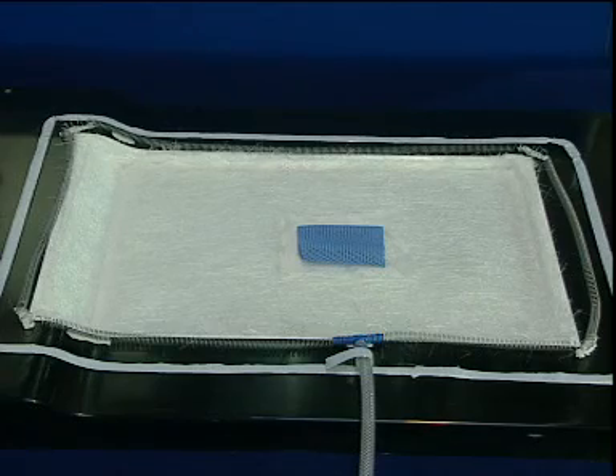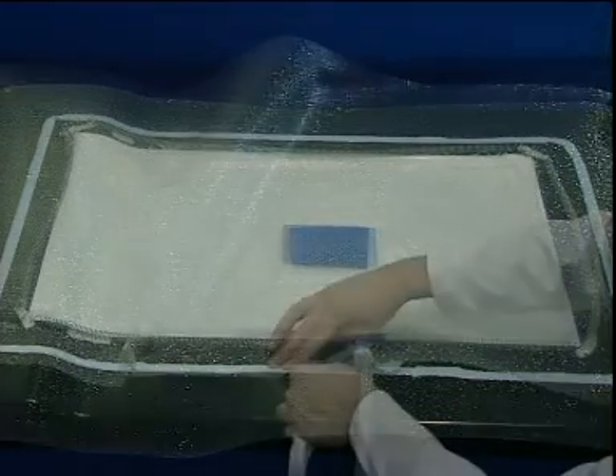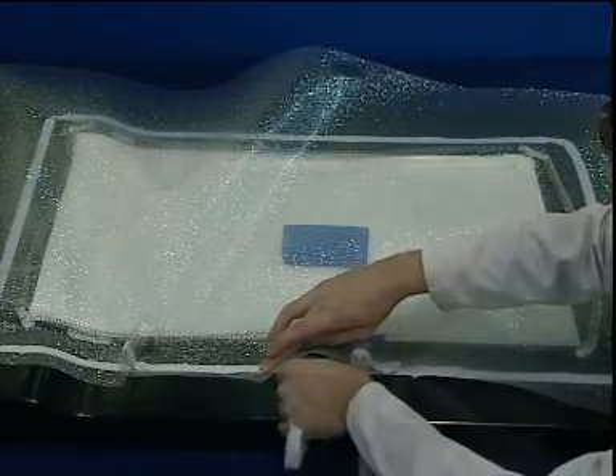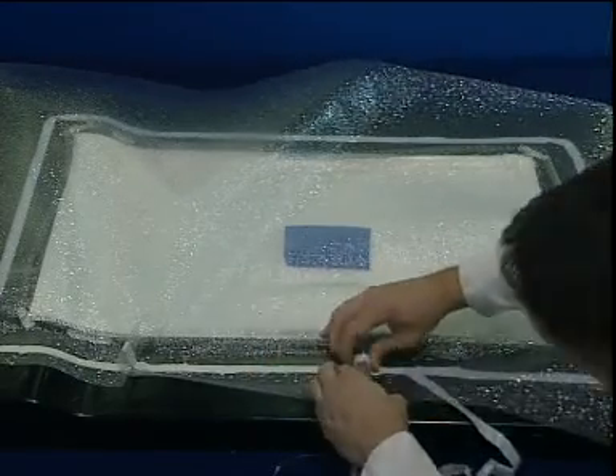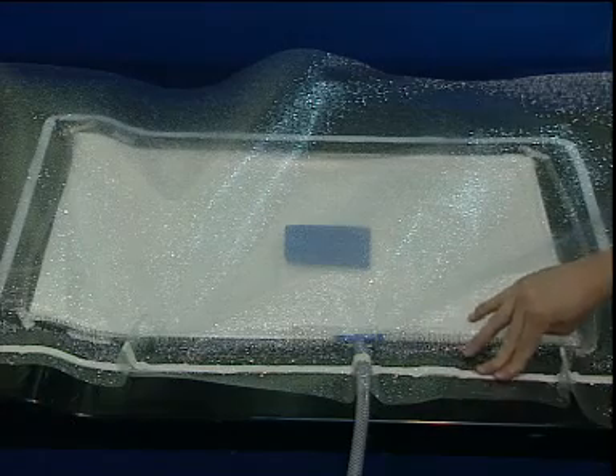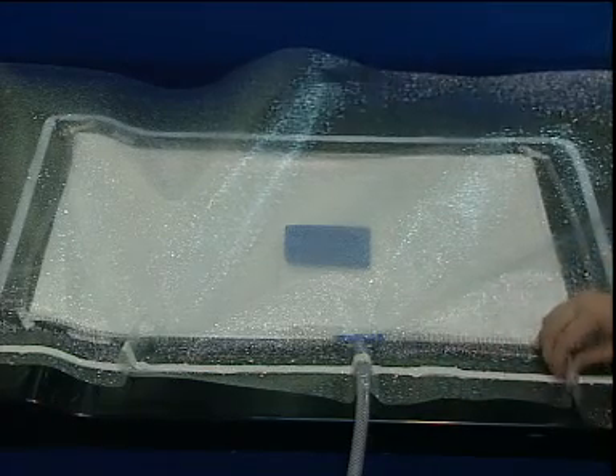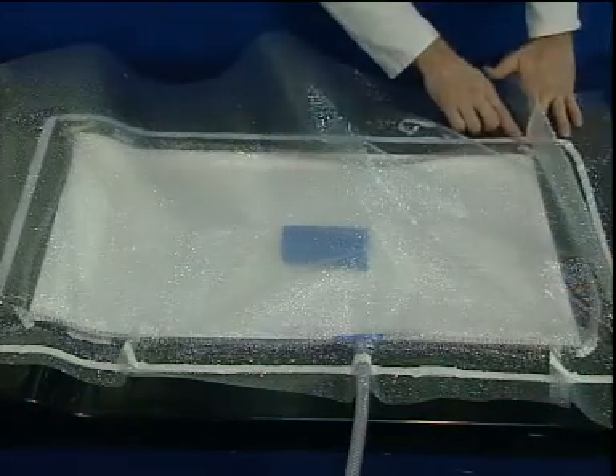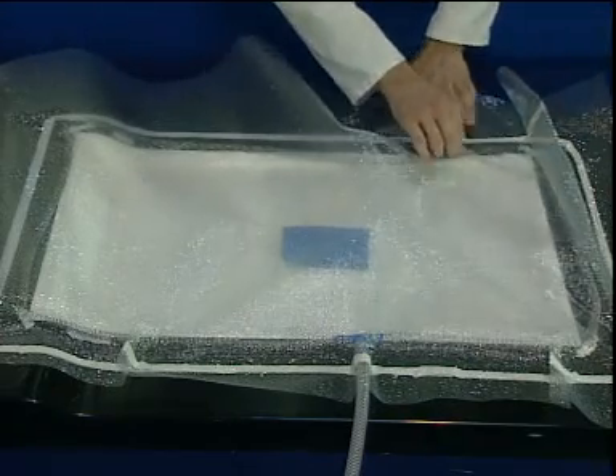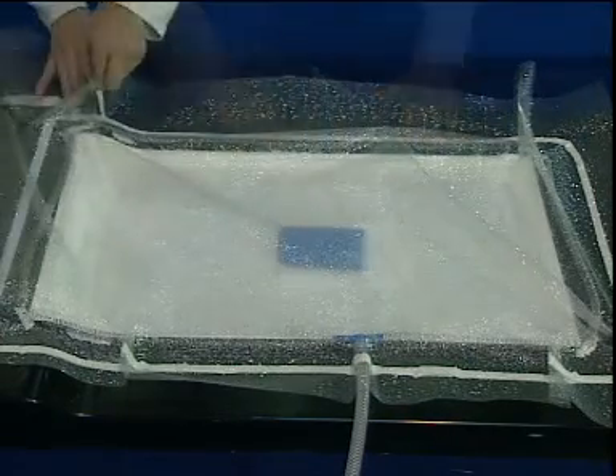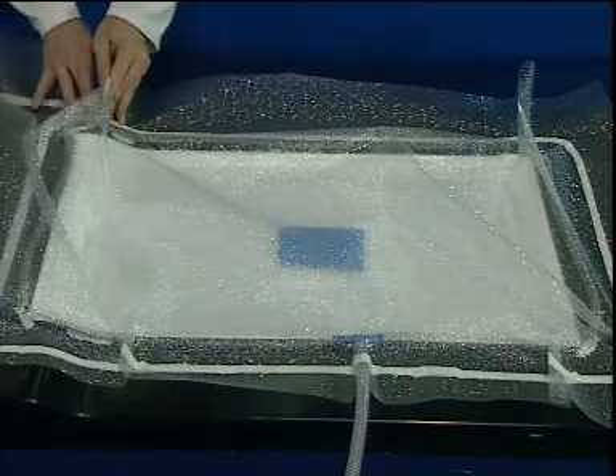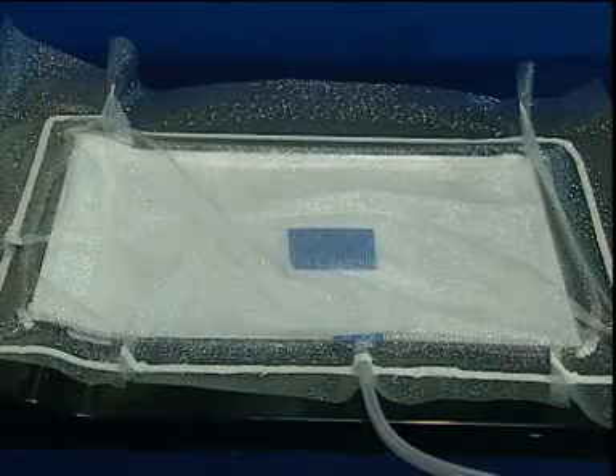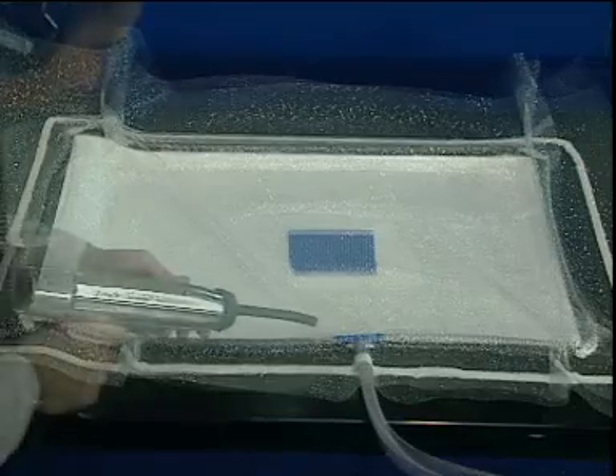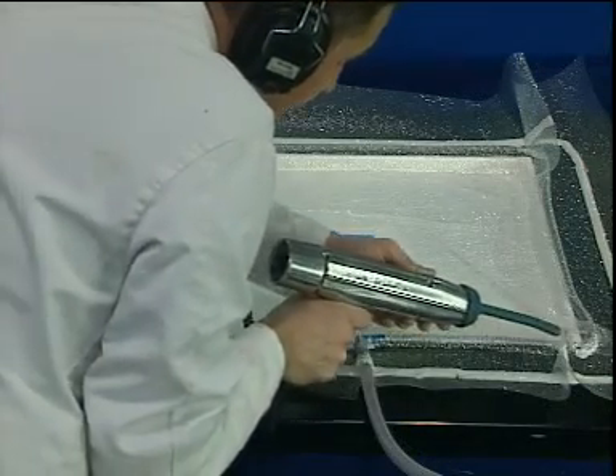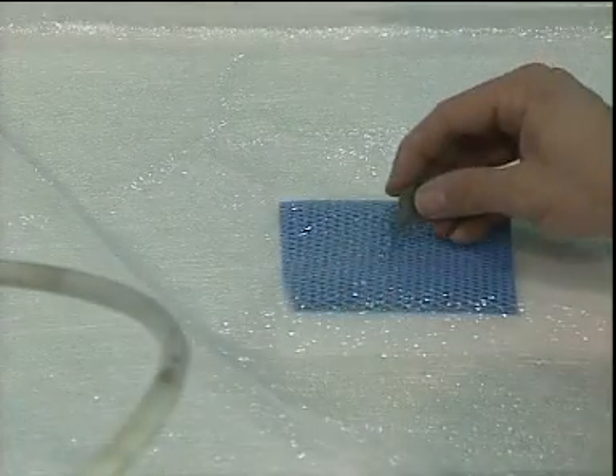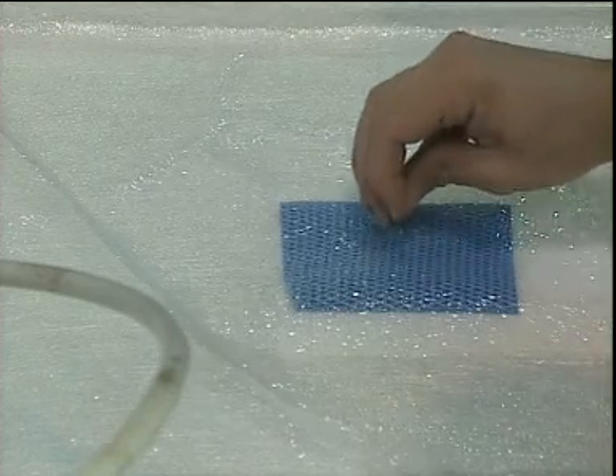The key to vacuum injection is a textured film which allows excellent resin distribution with no additional layers over the laminate. The moulder should ensure that there is enough film to take the shape of the moulding. Up to 50% more film than moulding area may be required. The film is sealed carefully using the tape. Pleats are used to ensure that there is no bridging of the film. A vacuum is applied and the film checked for leaks. Finally, the film is slit and a tube attached in the center.